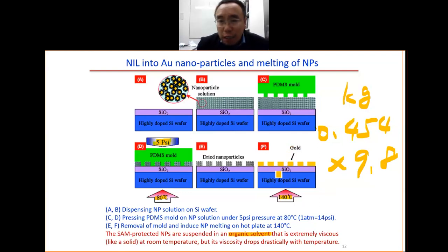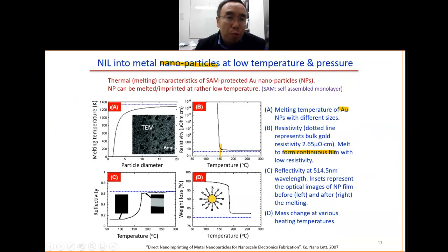You may wonder, how come we get these sharp corners? If the gold on the substrate got melted, you would have something like a ball, right? Because of the surface tension, the melted gold should have a spherical shape. But in this case, it is melted only momentarily. The nanoparticles got melted, but once they come together, you get this big gold. It is no longer nanoparticles, so the melting temperature goes up right away. The melting point here is 140 degrees, but once merged together, the melting temperature becomes much higher. That's why I said you cannot do imprint into the gold at 150 degrees, because once they get merged, the melting point goes up right away. It no longer flows.